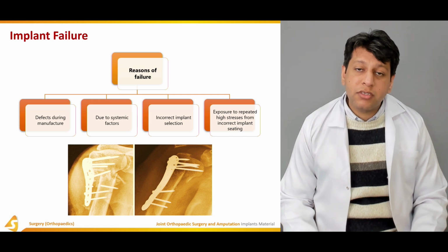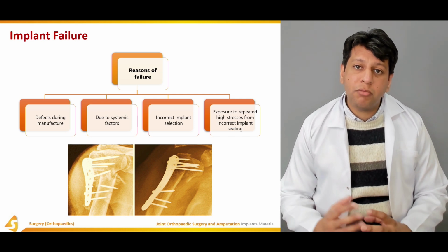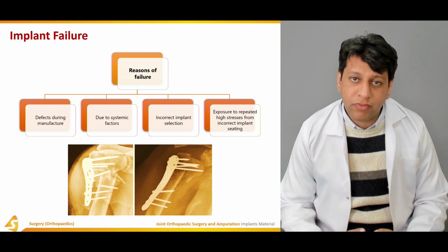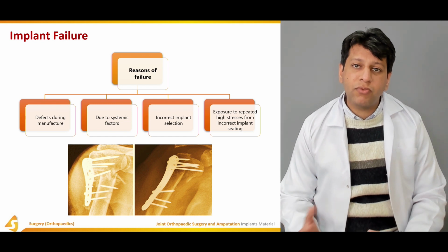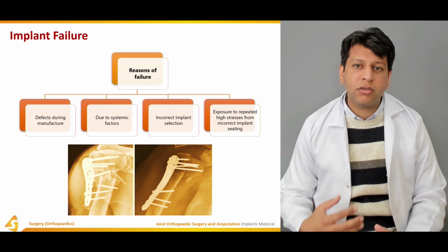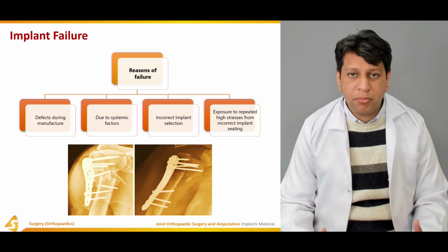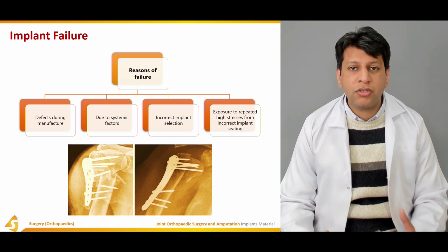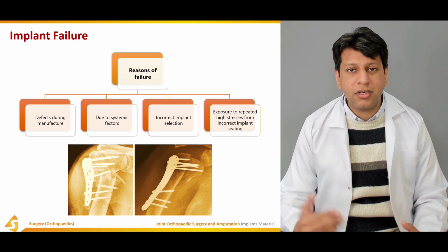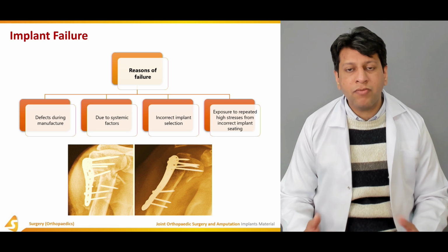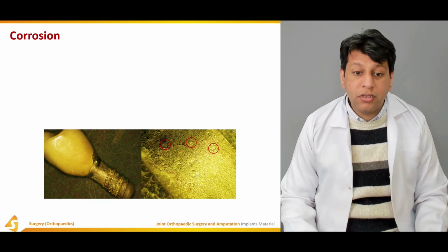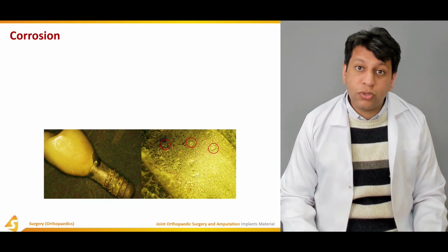Sometimes what happens is, despite all the effort, we are not able to correctly reduce the fracture fragments. And usually once this happens, due to a combination, or could be due to problems with the bone, or osteopenia or osteoporosis, then certain areas have increased stress, and this leads to screw breakage and eventually implant loosening.